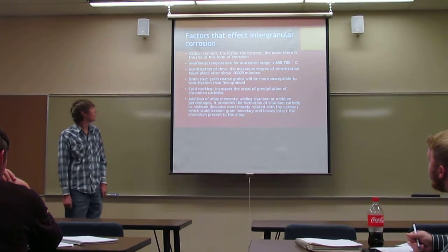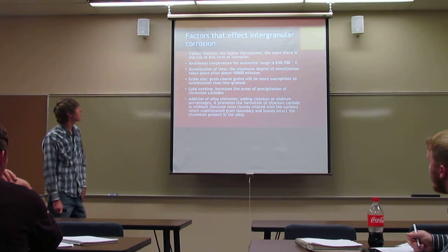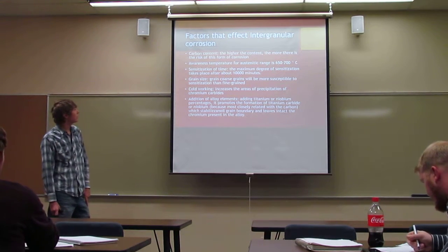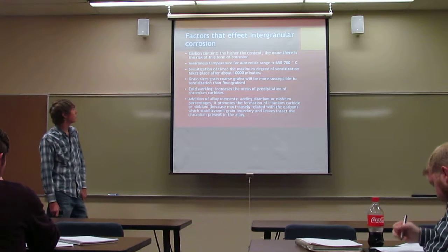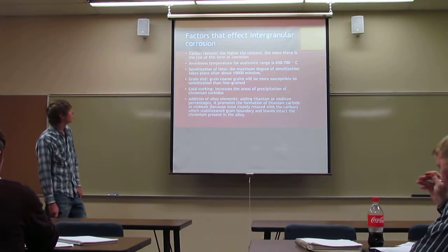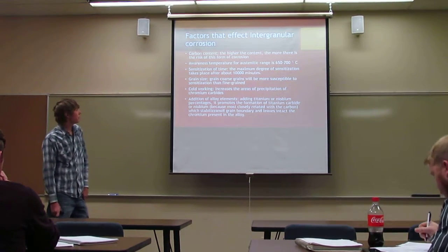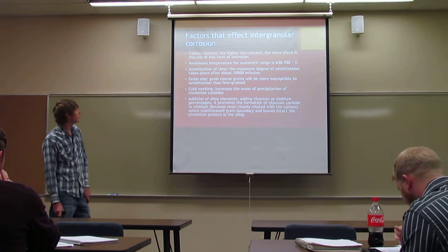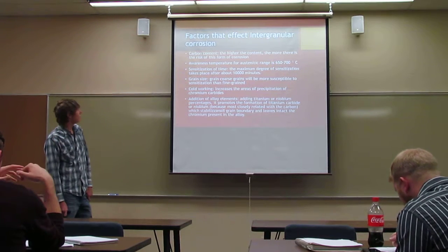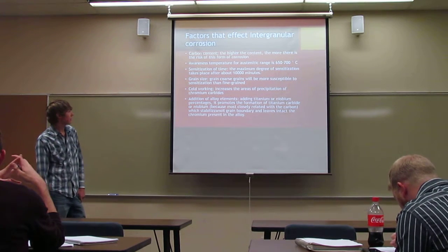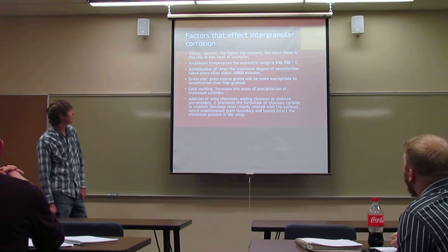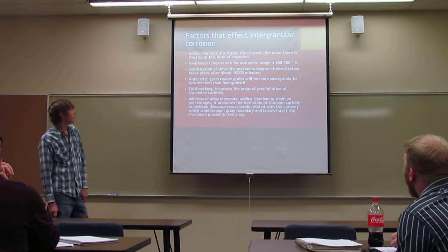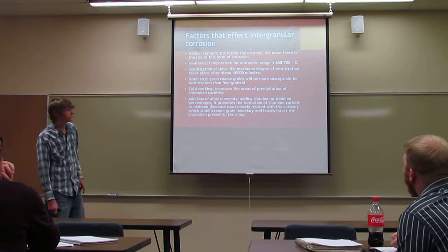The factors would be carbon content. The higher the content, the more risk of this form of corrosion. The temperature range would be between 650 and 700 degrees Celsius. Sensitization time: the maximum degree of sensitization takes place after about 10,000 minutes.